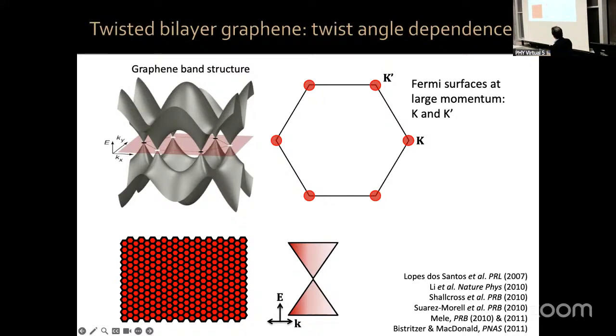If you have a single sheet of graphene, this is the electronic structure, Dirac cones. We have the K and K prime valleys. This is the Brillouin zone and the reciprocal lattice. And if you have some finite Fermi energy, cutting your Dirac cone at some finite height, you have these Fermi disks.